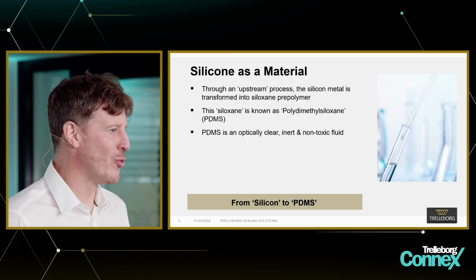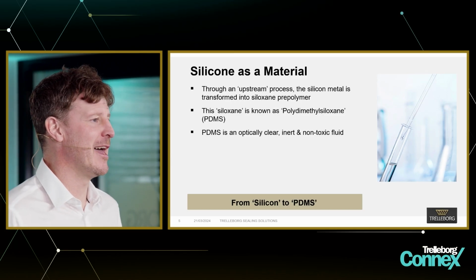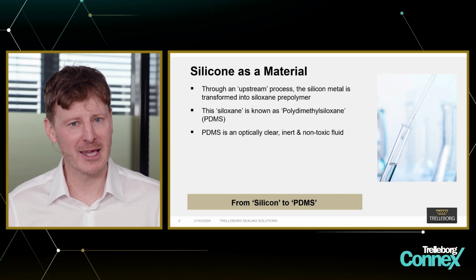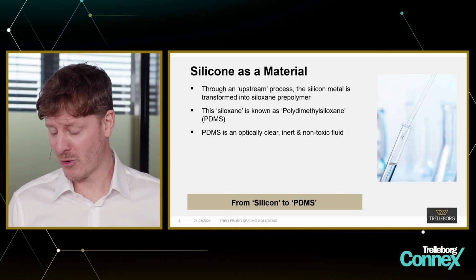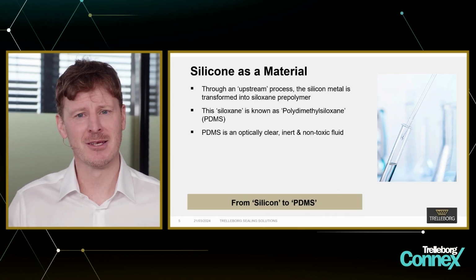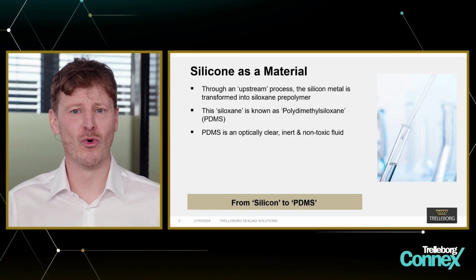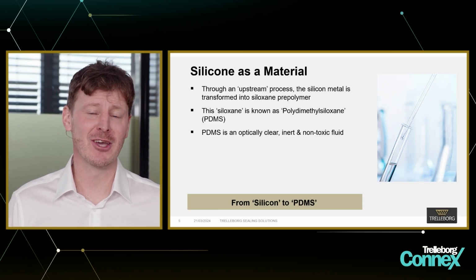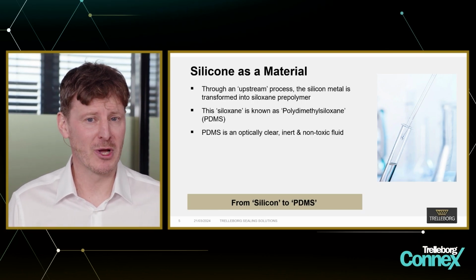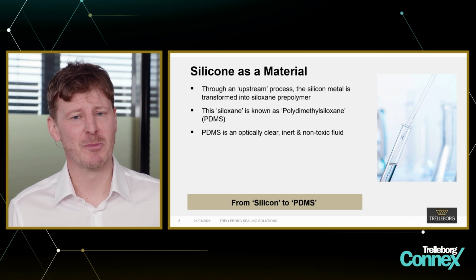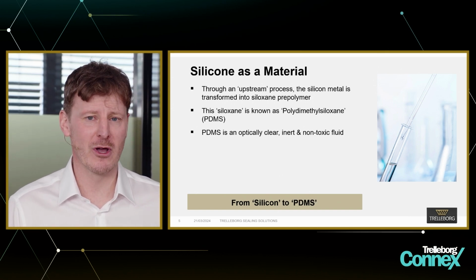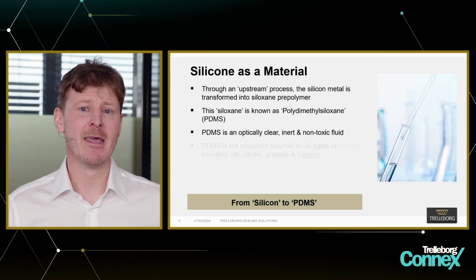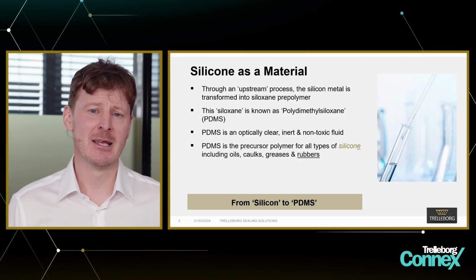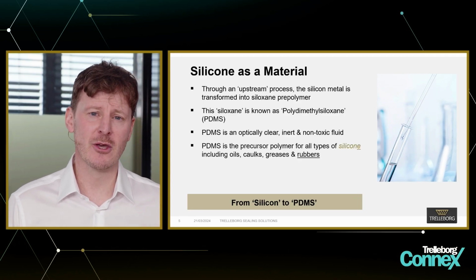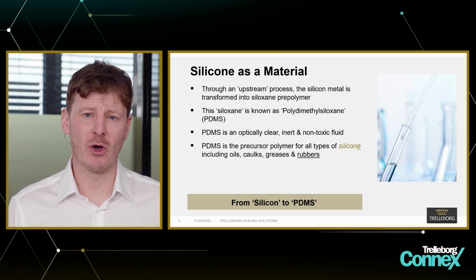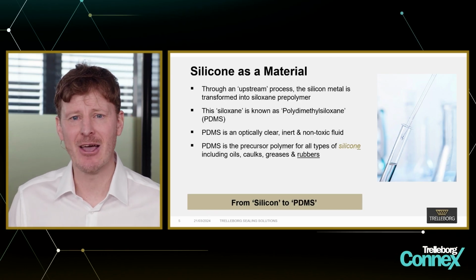I think it's quite important to say that those three bullet points there do cover a lot of very complex chemistry, and quite honestly, it's difficult to envisage how this metalloid is transformed into a clear, colourless liquid. But it does happen through chemical exposure to chlorosilanes, methyl chloride. It goes through a reactor. And so what we get is this fluid, PDMS, and this is the precursor polymer for all types of silicone. And this is where we add the E onto the end.